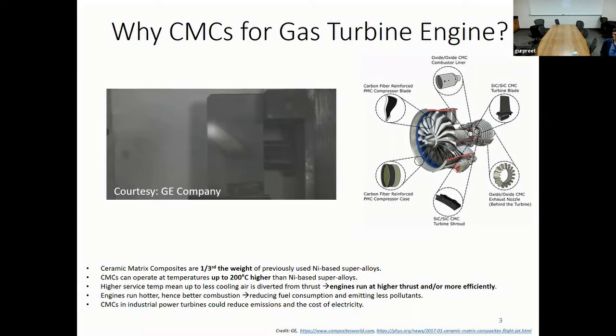Also, the ceramic matrix composites are able to operate at higher temperatures than nickel-based super alloys, so about 200 degrees C higher, which means in addition to saving weight, you are also able to burn your fuel at a higher temperature, which means better fuel burn efficiency and also lower emissions. And then the CMC-based parts also are able to run hotter, and so they do not require active cooling as is the case with nickel-based super alloys. So that also saves fuel and hence cost.